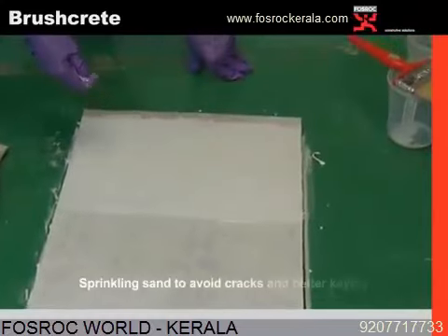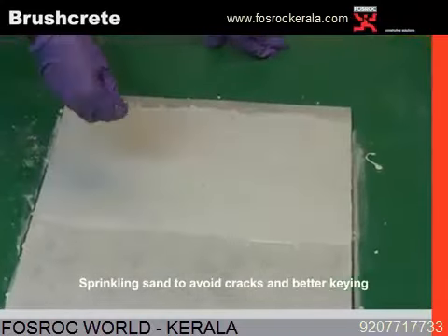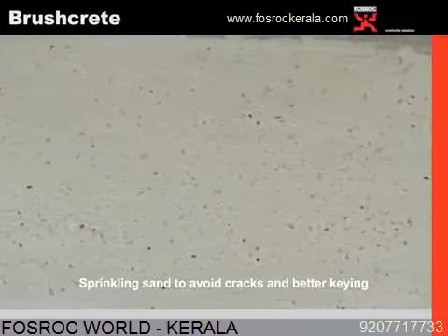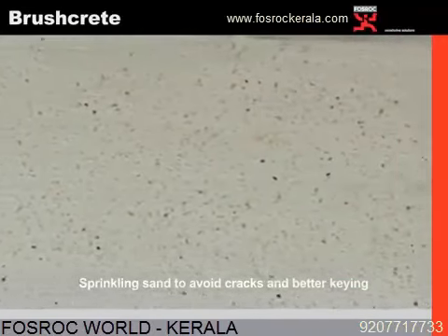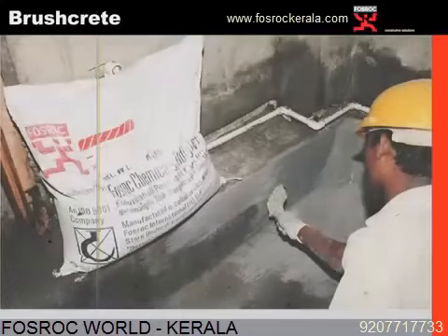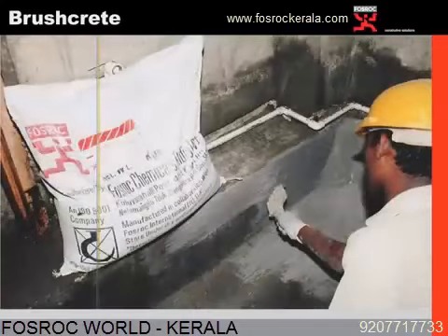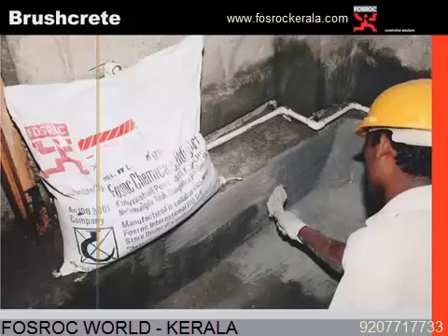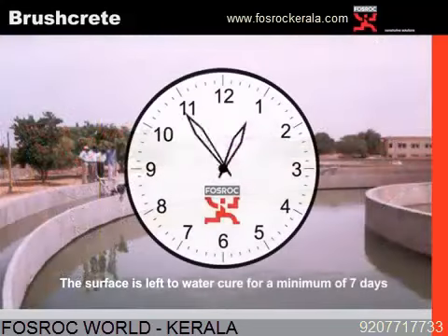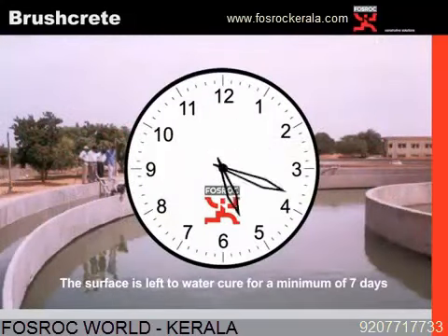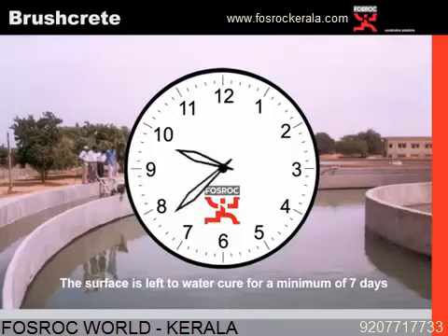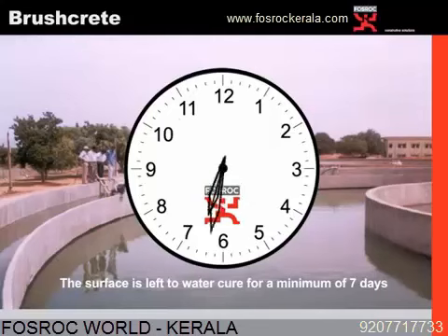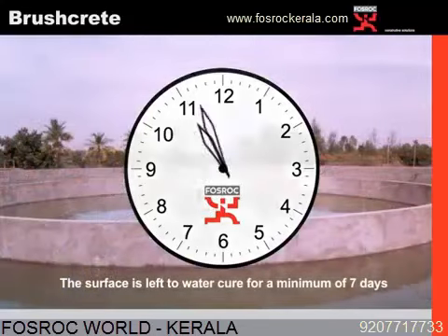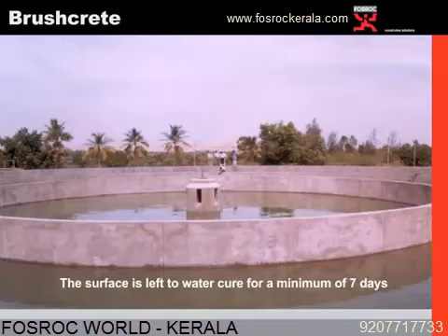Sprinkling of sand has two advantages. One, it avoids cracks appearing on the waterproof coating. Second, it will give us a keying effect for any mortars or screeds laid on top of this waterproof coating. Once the coating is dried, curing again becomes a very mandatory process, being a cementitious material. Ponding is the best way of curing the substrate.